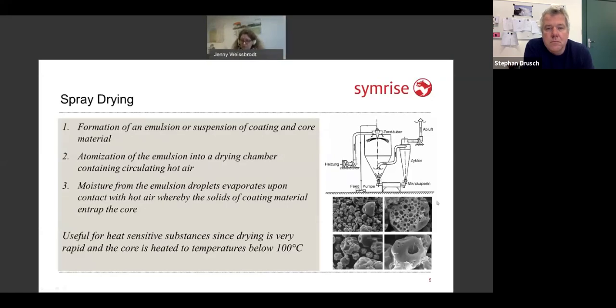You see you have your active, in this case a flavor, included in a matrix of your carrier material. This process is very useful even for heat-sensitive materials, because the temperature the particle really gets is always below 100 degrees C, and this is because the particles are cooled by the evaporation of water.